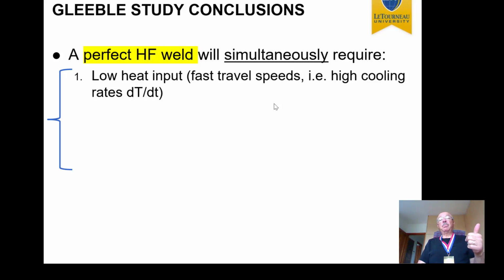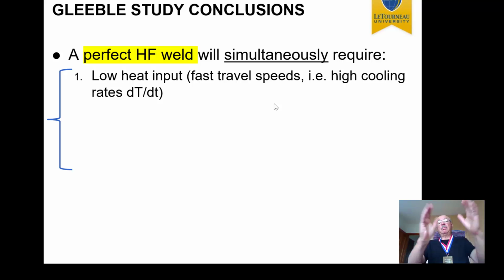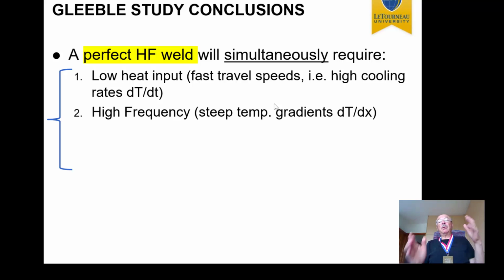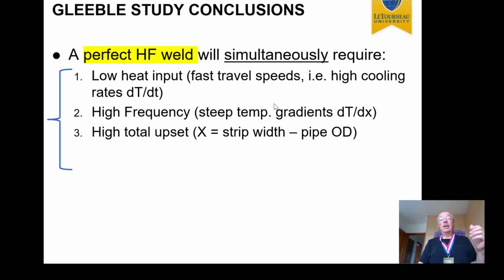So we concluded basically that for a perfect weld we would simultaneously require low heat input, which means in practice fast welding speed, that is high cooling rates. Imagine the pipe coming really fast. That's the only way you can accomplish low heat input. We also concluded that we have to use very high frequency, or the highest possible frequency, to make the gradient narrow and accomplish as much squeeze out as possible.